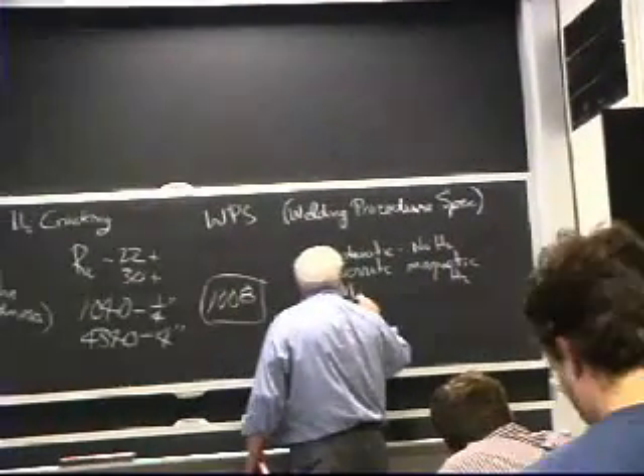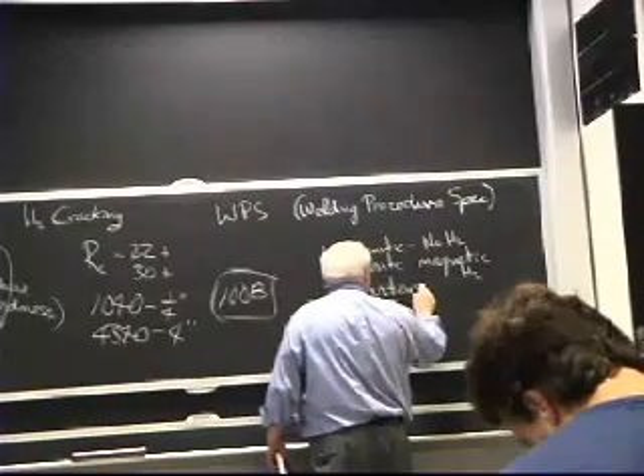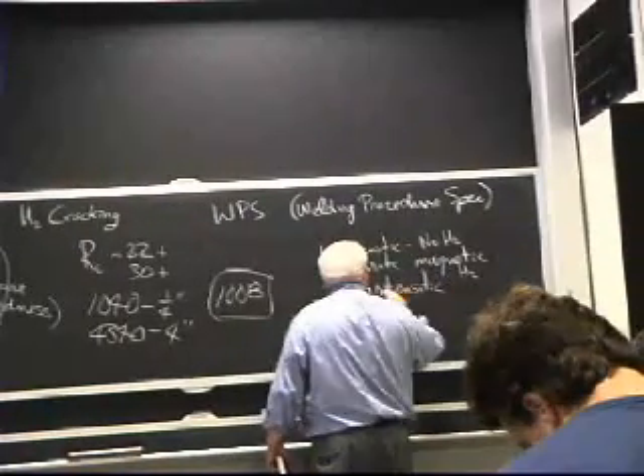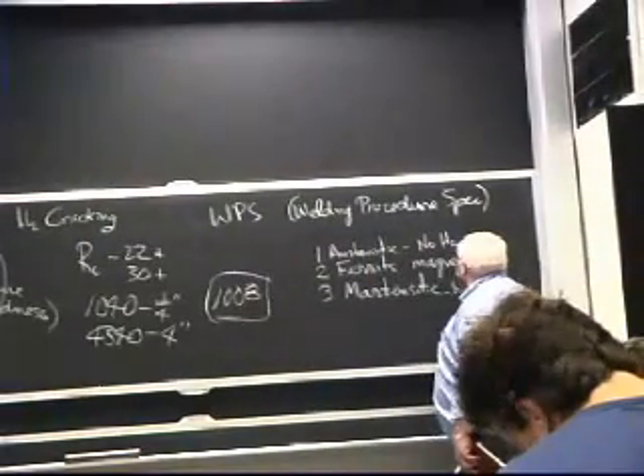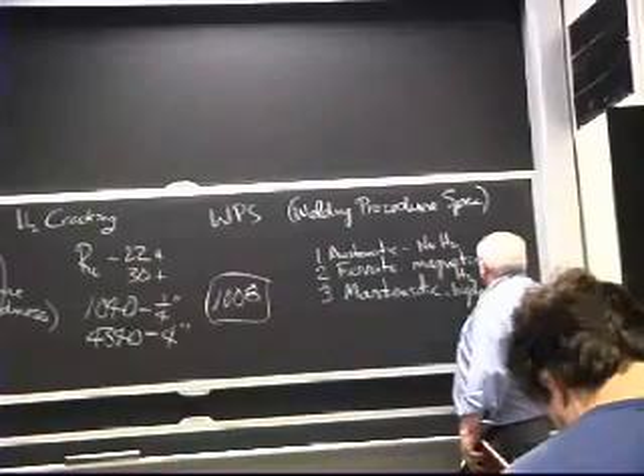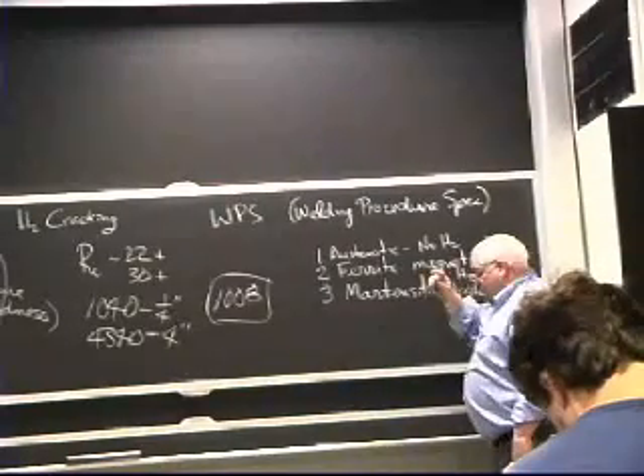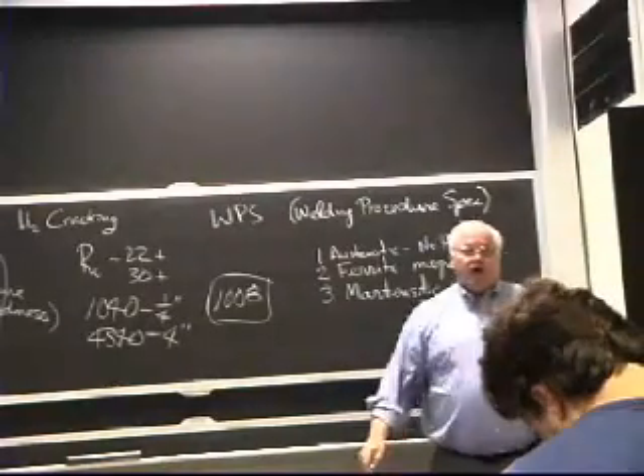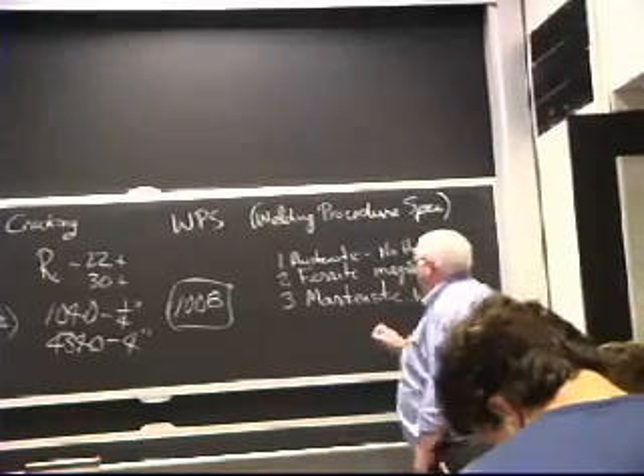And then there's martensitic, and these are very difficult to weld because they have higher carbon, so they have a higher carbon equivalent, and they are a similar crystal structure, and they are susceptible to hydrogen cracking. So they're very difficult, but they can be welded.